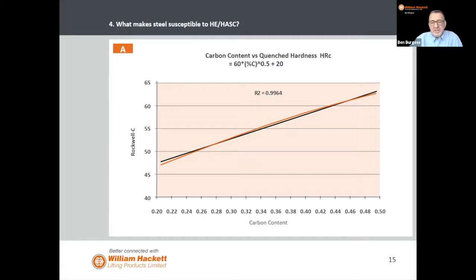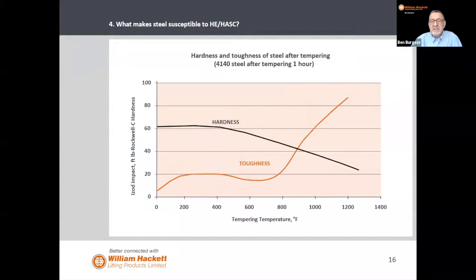The other subject we touched on there was heat treatment, and with Francois and Professor Rolf Mustert, they are absolute experts in this. So for a given grade of steel, if you temper it at 200 degrees for a very low period of time, you end up with a steel that is extremely hard and in effect would give you a good working load limit. However, its toughness is not very good. If there's a snatch on the load, corrosion, it's not great.